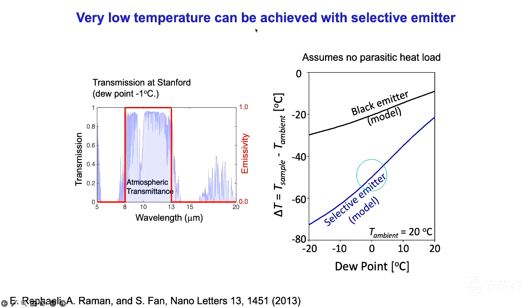The blue curve here is the simulated transmission spectrum of the air at Stanford University when it's quite dry. And you get about 90% transmissivity in the wavelength range of 8 to 13 micron. Using this, if you construct a selective thermal emitter, you will get a temperature that's about 40 to 50 degrees Celsius below the ambient air temperature. And that's what we predicted initially in the theoretical paper.